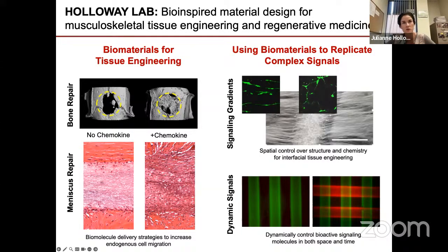Although of course, especially the hyaluronic acid, the fibers do swell and take on water, and so the fiber diameter becomes larger. So we do see the fibers can swell, but we do not see that they lose the overall fibrous mat morphology. One of the reasons for this, especially for these photoreactive polymers that we're using, is we cross-link them after electrospinning. So we get inter-fiber cross-linking as well as intra-fiber cross-linking, and that helps, I think, keep the fiber morphology intact.